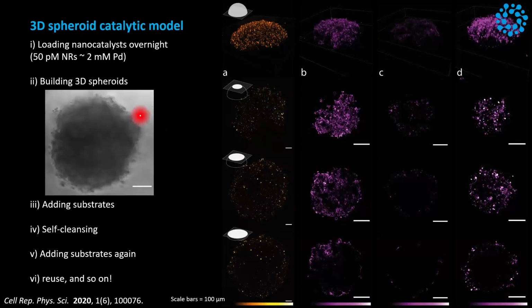And this is the kind of spheroid. So we have a lot of palladium nanoreactors inside this spheroid. And you see them because of the fluorescence. We put a fluorescence tag in the MOF here. And in this spheroid, you see different cuts of the spheroid. When you go to the middle, you have fewer of these nanoreactors, okay? And then we did this also for, I think it was 10 days or something like that. Basically, you have the model of the spheroid, and then you add the product. It goes inside the spheroid.